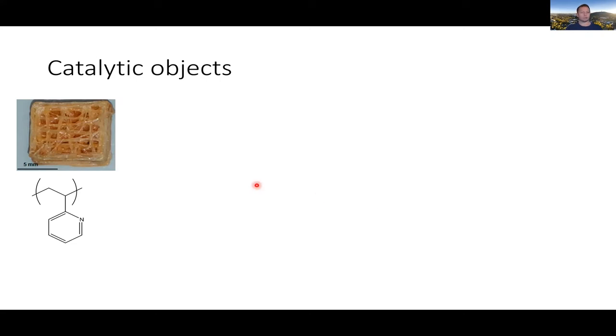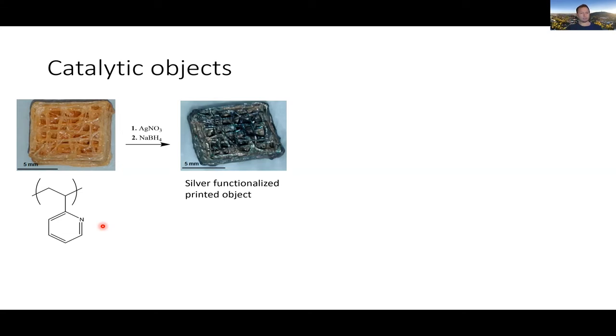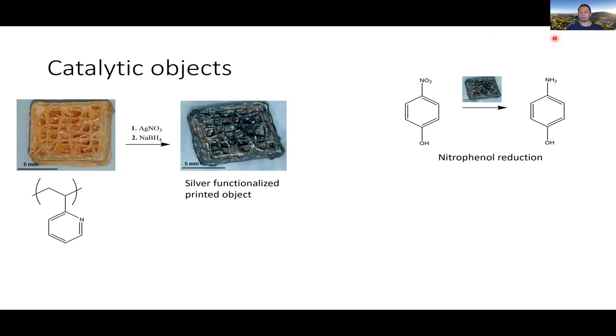In this case here, we have a catalytic object. So this pyridine group can actually be a ligand, and we can add, in this case, silver salt to this and then reduce that silver salt. And here we have a composite material where we've created a mesh. We're trying to get a high surface area, and then we put in silver embedded into that structure, and then we can use that silver to catalyze chemical reactions. That's what we did here with this nitrophenol reduction. And we can use that as our 3D printed catalytic objects here.